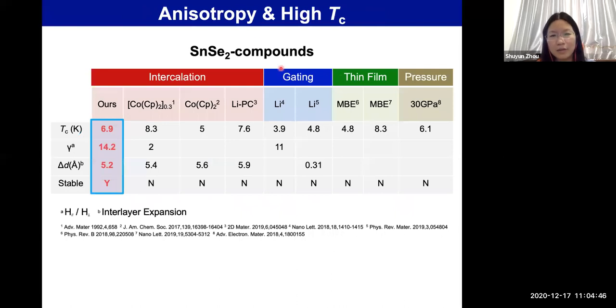Now, how is the superconductivity of this intercalated tin diselenide compared to superconductivity induced by other methods? Here I show you a table summarizing superconducting tin diselenide using different methods, ranging from intercalation, gating, or thin films, and so on. And here we show that our intercalated tin diselenide has a quite high transition temperature of 6.9 Kelvin. This is much higher compared to the gating method, and at the same time, it has very high